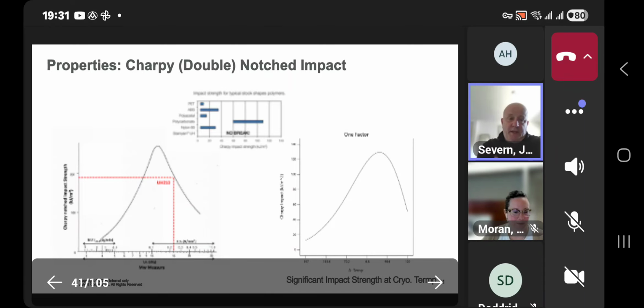So just to give you an idea of what we're like, in Charpy impact tests, ultra high passes all the time. We have to have a double notch impact test there for ultra high. And you see from the left-hand side that the peak in impact strength comes around about 1 million. So we have a low molecular weight, low impact strength, around about 1 million we peak. And then after that, we drop off. And that's because we're moving to different fracture mechanisms. The graph on the right-hand side shows you that even with a double notch impact test, you still have impact strength down to cryo temperatures. So this is why you see liquid nitrogen dewars with white ultra high linings. So it still has impact strength even at cryo temperatures. Next slide, please.